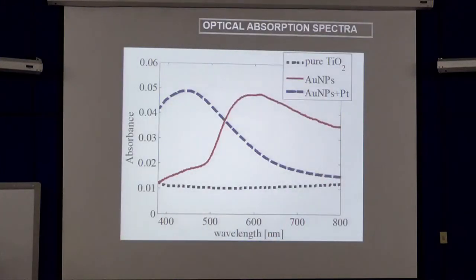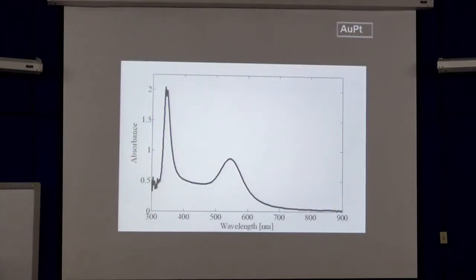When you put in the sample a different element, for instance platinum, you can switch the position of this peak, as you can see in this spectrum. But also, you can originate a different peak with the same sample. So it corresponds to platinum and it corresponds to gold in a bimetallic sample.